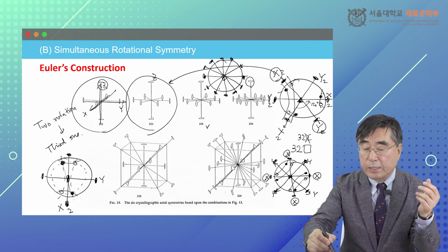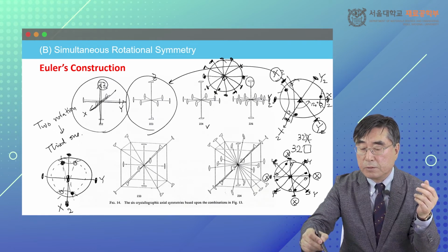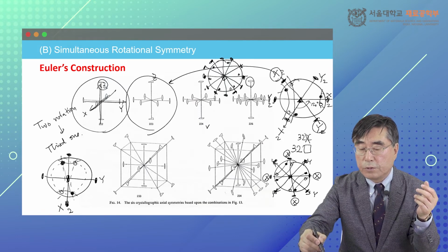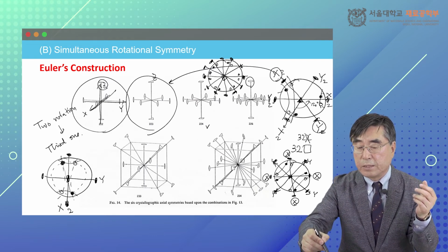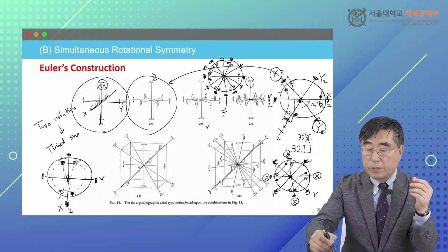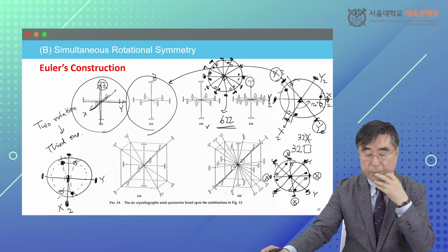So if I generate any poles, then again 6 poles, so 60-degree rotation, 60-degree rotation, 60-degree rotation, and 2-fold, 2-fold. Am I right? Sorry, something wrong. 2-fold and 2-fold. So it generates 12. Yep, 2-fold, 2-fold in here. So 12 poles. That's what we call 6-2-2 rotational elements.